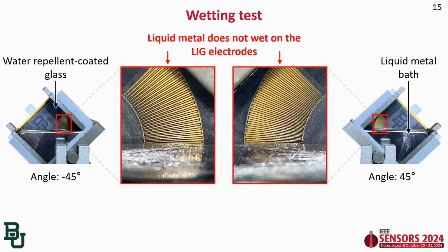Here are the optical images of the tilt sensor and the tested surface when the sensor was tilted. The sensor was tested by tilting 100 times in clockwise and counterclockwise directions between minus 45 degrees and 45 degrees. From the close-up images of the LIG electrode, it is quite apparent that there was no sign of surface wetting by liquid metal on the sample.